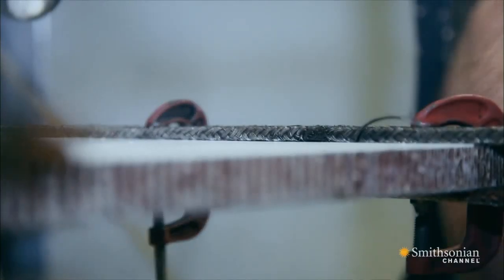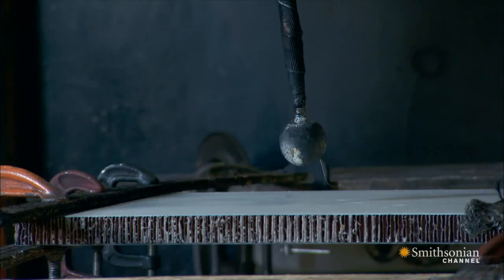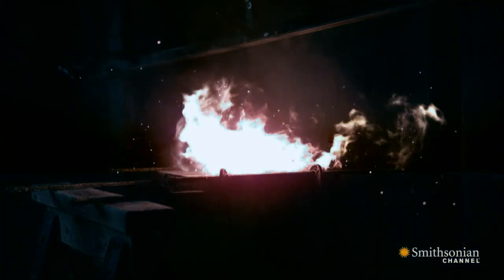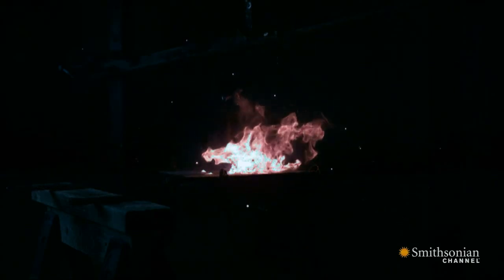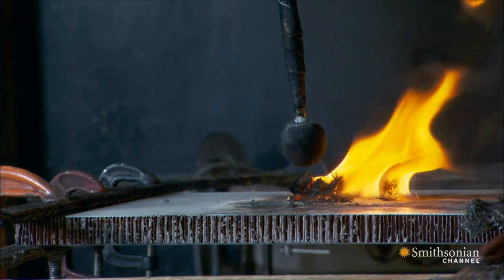Next, a carbon composite panel without the inbuilt metal protection. As lightning strikes, the non-conductive material resists the flow of electricity through it. This causes it to heat up to several thousand degrees and burn. Carbon fiber composites are only about one thousandths as conductive as an equal amount of aluminum — it may get hotter, it may burn, if nothing is done to adequately protect it.